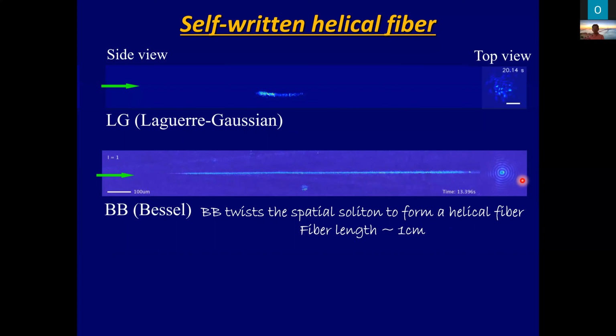The laser beam propagated inside the fiber. The transmitted beam still exhibits a donut intensity profile. A Bessel beam twists the spatial soliton to form the helical fiber with a fiber length over the centimeter scale. And this fiber can deliver an optical vortex field, namely the Bessel beam.